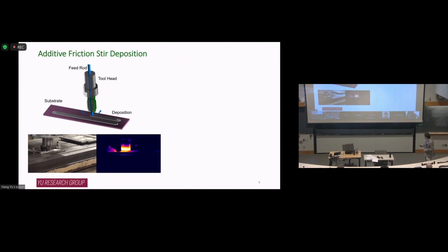Once the feeder material is beneath the print head, the print head is also rotating, right? So the print head can impose compression and shear to further plasticize the material. It's like a smearing process. So during this process, the feeder material, which is in the form of a solid bar, will become fully plasticized because of compression and shear. But not just the feeder material. Usually, the surface layers of the substrate also get plastically deformed and mixed together with the feeder material. So by doing this, you can get a really strong interface bonding.